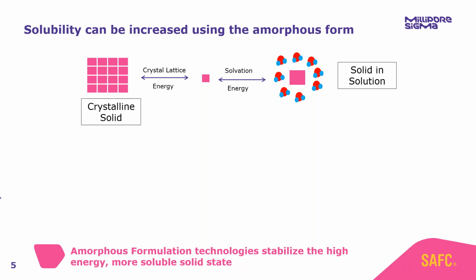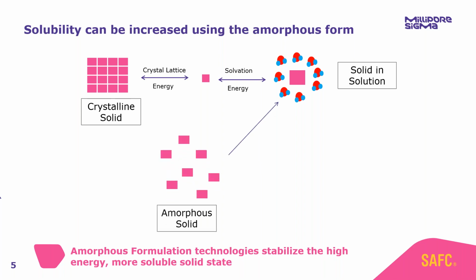There's not much we can do about the solvation energy. This is typically associated with the polarity of the solvent and the polarity of the molecule. But what we can do is reduce substantially the amount of energy required to break those associations. We can use a different solid state, the amorphous solid state, chemically identical, but no longer held together in a crystal lattice. And therefore, if you simply balance thermodynamics on each side of that equation, energetically speaking, you require less energy to break those interactions apart, and therefore the solubility of the amorphous solid becomes substantially higher as it's simply thermodynamically more favorable.